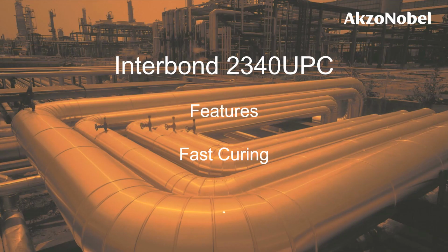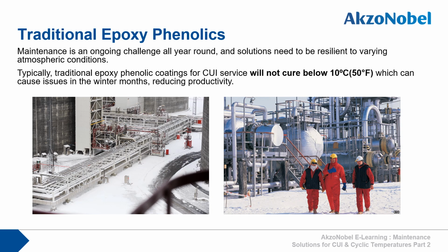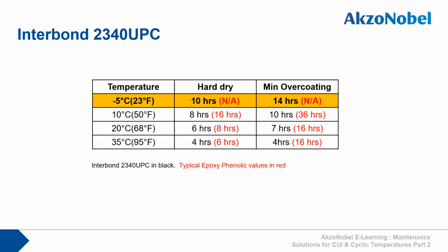Okay, let's look at 2340 UPC's features in more detail, starting with its fast curing property. Typically, traditional epoxy phenolics will not cure below 10 degrees Celsius. Issues such as maintenance project delays can then happen when temperatures drop overnight or when maintenance needs to be carried out in the winter months. Conversely, 2340 UPC can be used down to -5 degrees Celsius, being hard dry in 10 hours at this temperature. As you can see in the table, 2340 UPC has faster hard dry times and has much lower overcoating times than traditional epoxy phenolics.